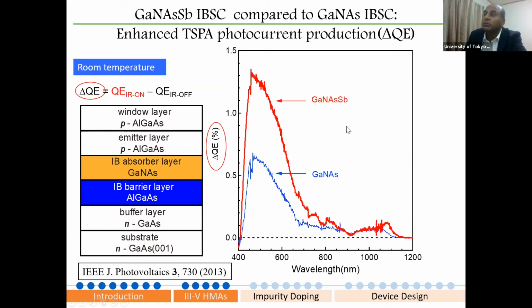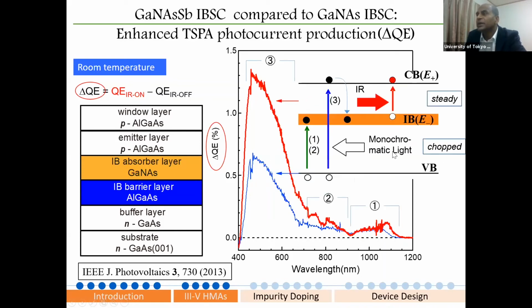And if you put some amount of antimony in your dilute nitride, because it is well known that if you put nitrogen in gallium arsenide, you have a lot of defects. To avoid that kind of defects or vacancies or antisites, we put some amount of antimony, and I show you that we can improve the materials and we can improve the photocurrent production, but still this is very low, okay? And I'm explaining here how we can explain this kind of photocurrent production using this intermediate band.